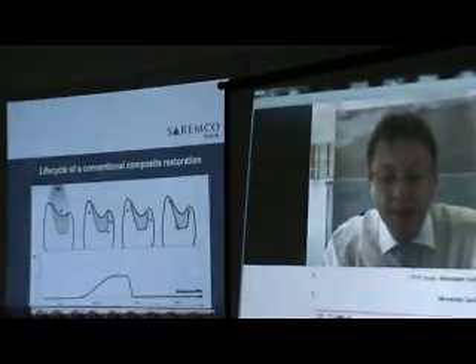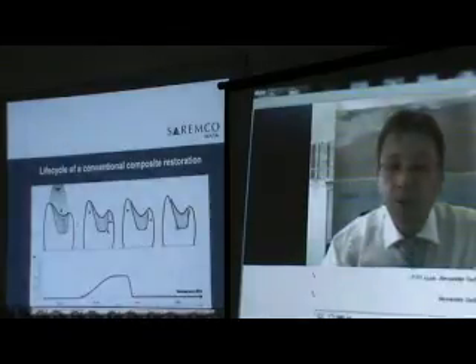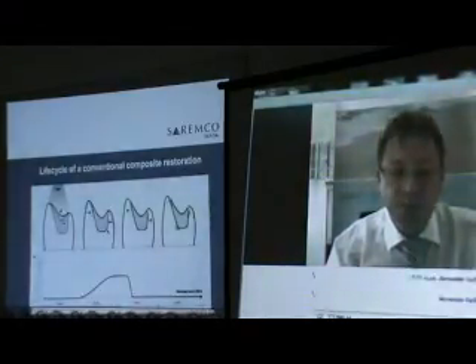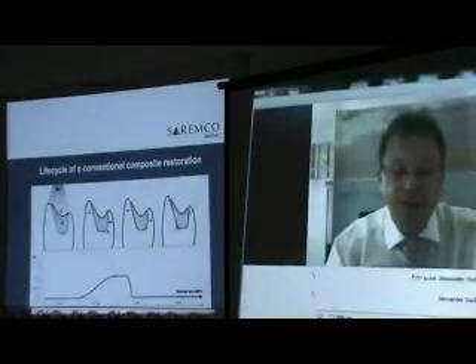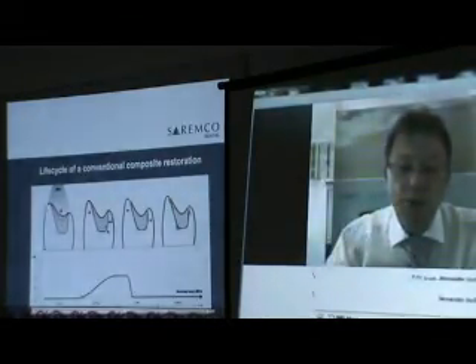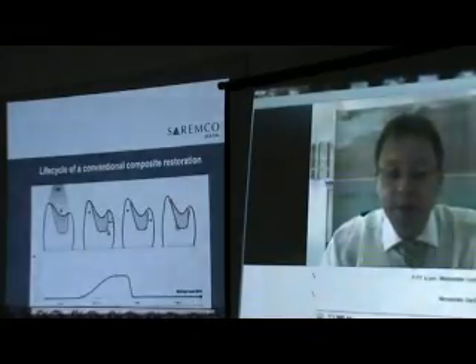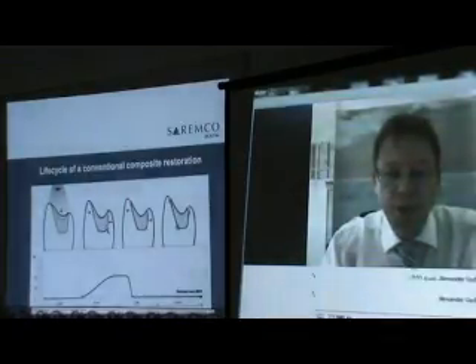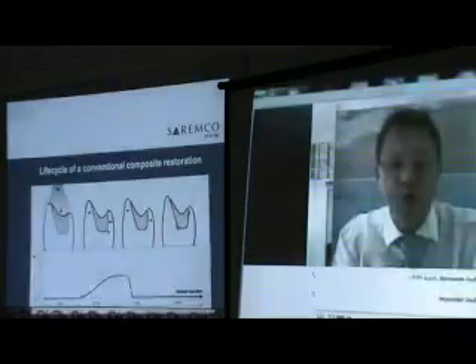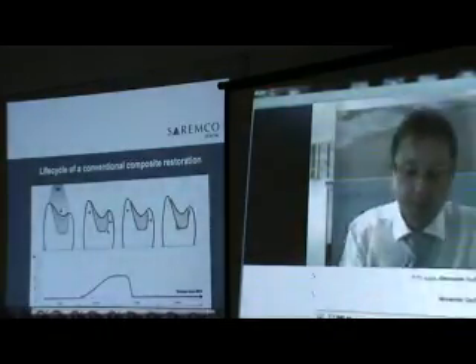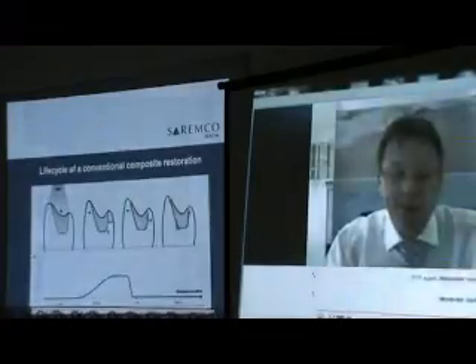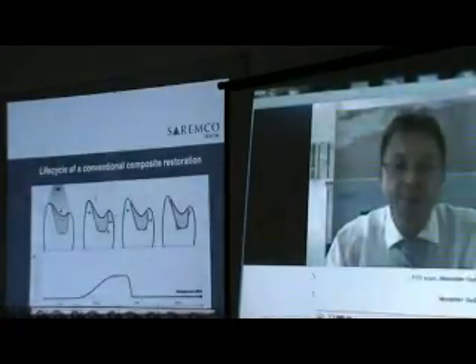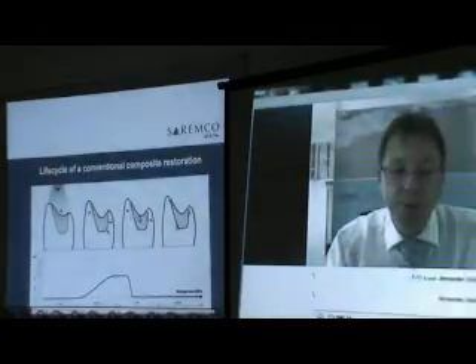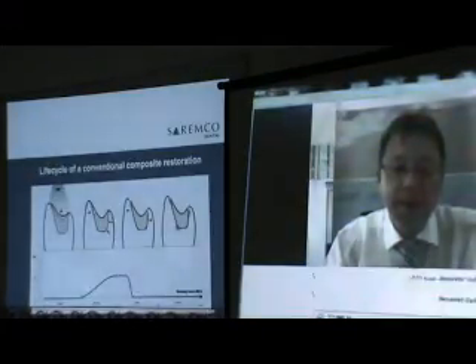see this small line, during light curing, the composite will shrink in volume. But as you see on the second picture, already after a few seconds, the composite will actually reach the so-called gel point. The gel point is the moment when the composite is more solid than soft. Now, as soon as this gel point is achieved, the composite will start to pull on the dental walls and therefore will deform the dental cusps.